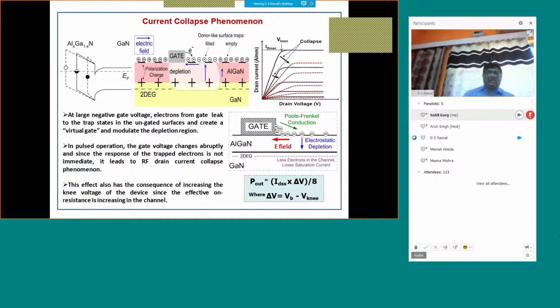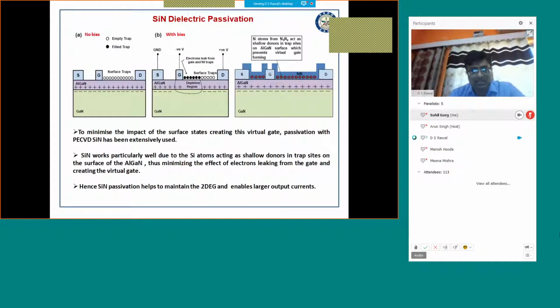And you can see that this is a virtual gate formation process, which I think was explained by Professor Dipankar Shah, so I will not go into detail, but the basic idea is to maintain the initial charge state of the aluminum gallium nitride layer, because during reverse bias, when we apply negative voltage at the gate, electrons leak through the gate, and they basically compensate the positive charge at the surface, and hence deplete the 2DEG, which ultimately results in the reduction in the two-dimensional electron density, which reduces current and increases the resistance, and this results in current collapse, which is basically reduction in the current and increase in the resistance, and ultimately the power performance is degraded.